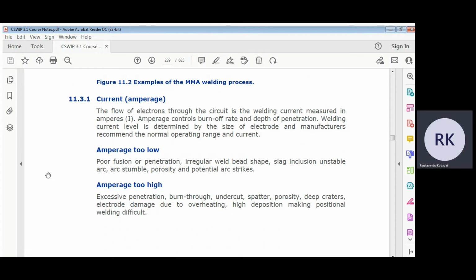So what happens if the ampere is too low or high? If it is too low, poor fusion. If you are using a 2.5 electrode and you have the current requirement of 110 ampere, but you are having 90 ampere only, then what will happen? There will be poor fusion or penetration, irregular weld bead shape, slag inclusion, the arc will be unstable and will stumble here and there. Then porosity and potential arc strikes will happen. The electrode will not burn properly. It will start, stop, and then you will get a lot of potential arc strikes, because the electrode will go here and there, and the arc will strike on the parent material also.